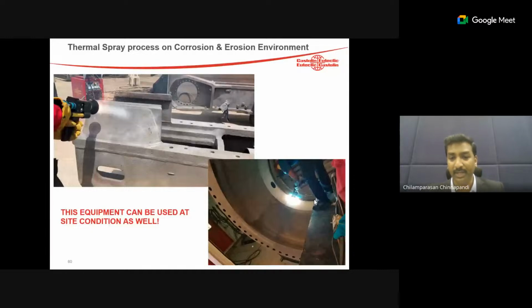This is the butterfly valve, 8-inch valve, 80 inches valve. We have done it for one of the power plants in Ruwais, and they were using a copper shim to protect this, but it failed within a few months, and they came to us for a solution, and we gave specialized coatings which have run almost 2 years, and it's still in intact condition. Now, when they get a new valve from the manufacturer, they are not just installing it, they are giving it to us. We do the thermal spray coatings with the specialized wires, and they take it and use it in the plant.